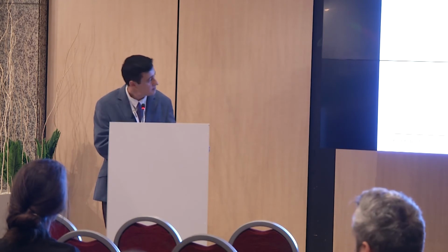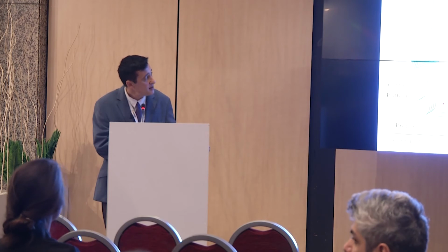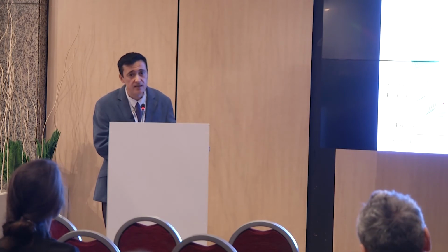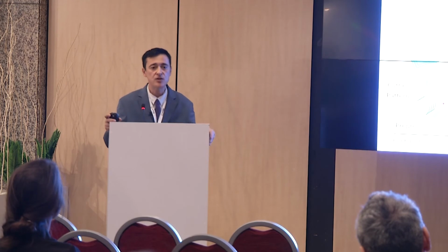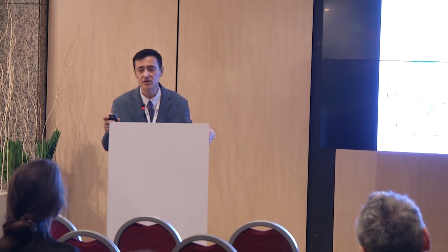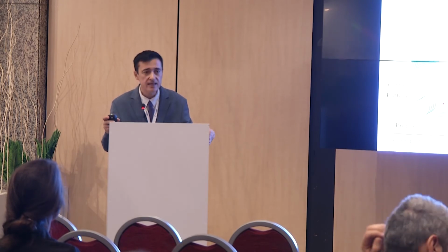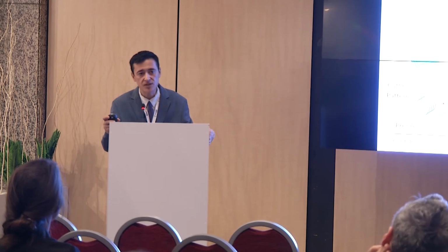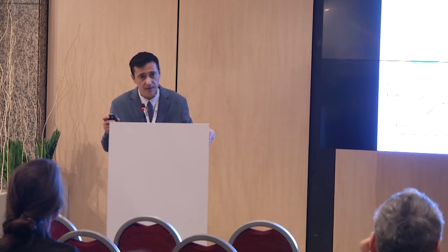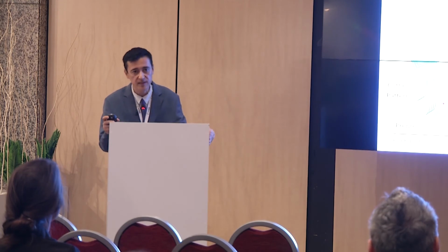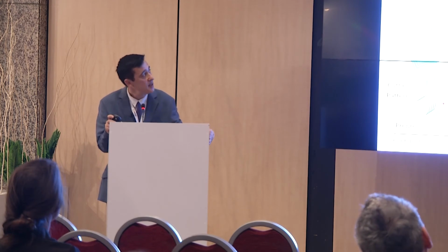And of course, when we look at the aging tests, it is providing a very positive result. When you mold it with a classical prepreg, within 10 minutes it is possible to manufacture pieces. However, when you look at the real performance time, you see different timing. First of all, you need to cut the piece after production, according to the shapes and sizes that you want. So you're going to spend time, and then you're going to preform it. And there is a certain time for that.